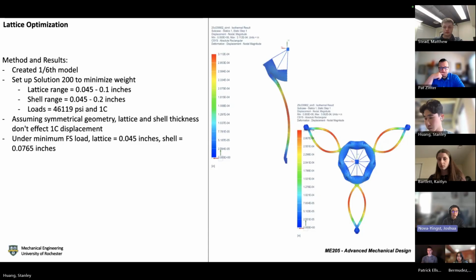The big one was doing the load-based optimization. For both of the models, we used a lattice and shell range, with the minimum being the minimum print thickness we were allowed, and the maximum being an arbitrary value that we assumed, because if it gets much bigger than that in the arms, you're going to have mushing and interference. You're not going to see a shell versus a lattice, just some weird air gaps. So we set that as a limit. From that load, the solver said the lattice should be the minimum thickness we told it, and the shell could be reduced to about 0.07 inches thick.